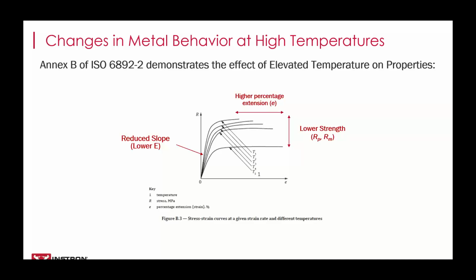Another thing that we see is that the onset of plastic deformation occurs at lower stresses. This makes sense for the same reason as the modulus is lower. Because the atomic forces are weaker, they'll be easier to break. And so less force is required for the same specimen to break those bonds.